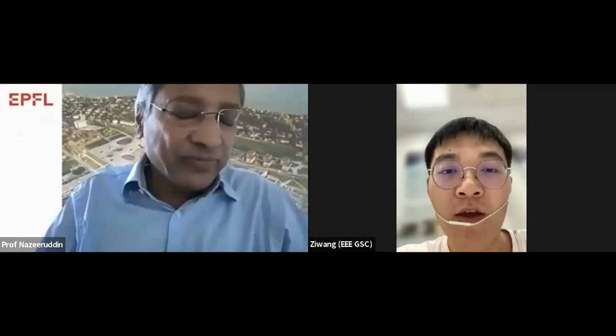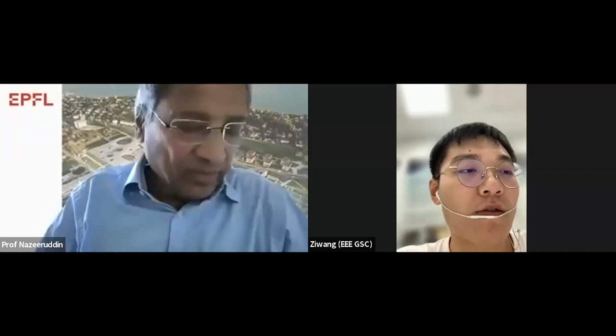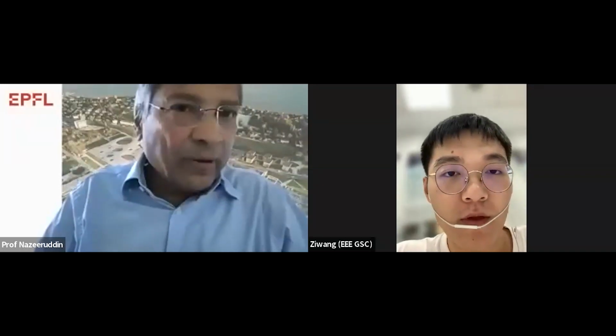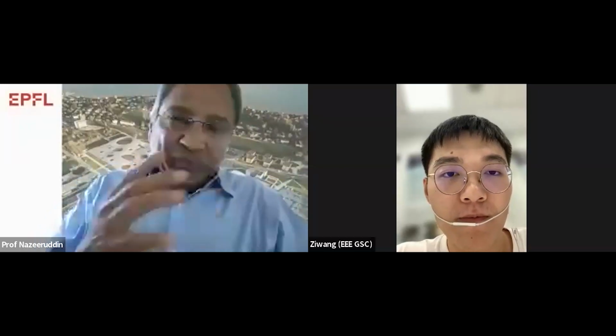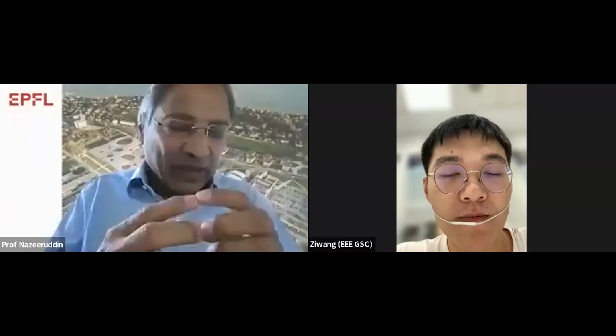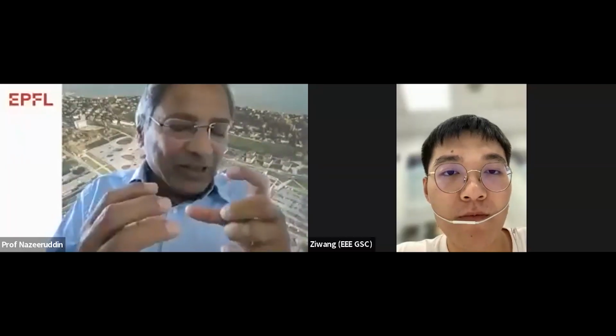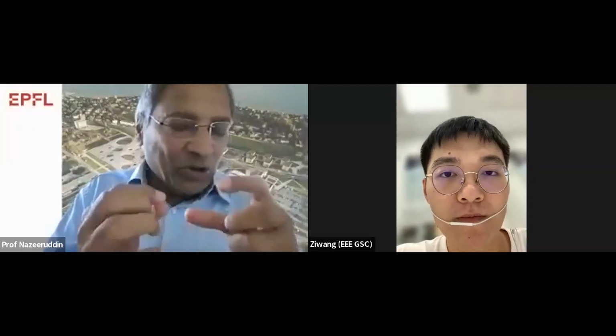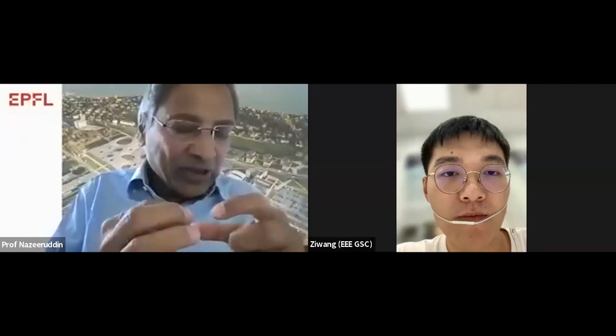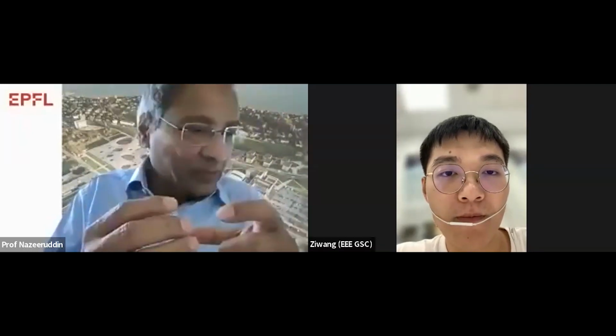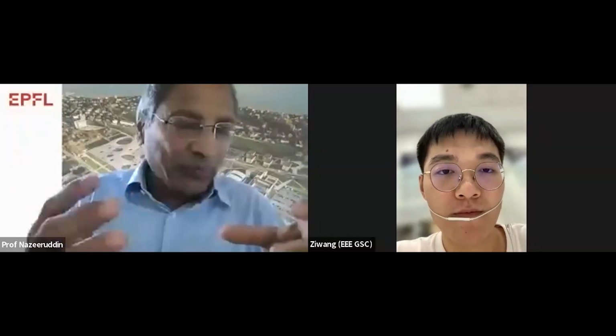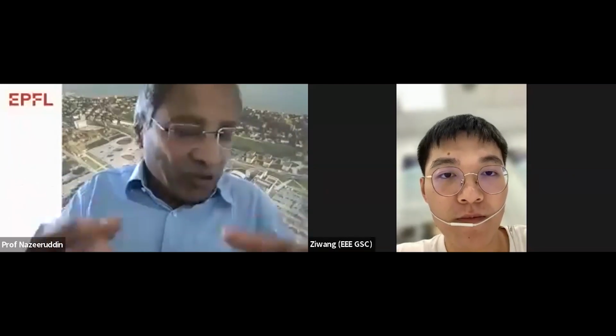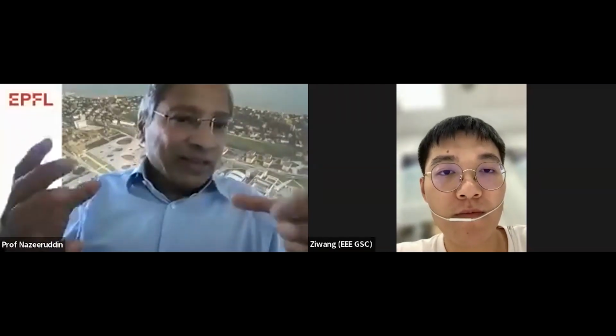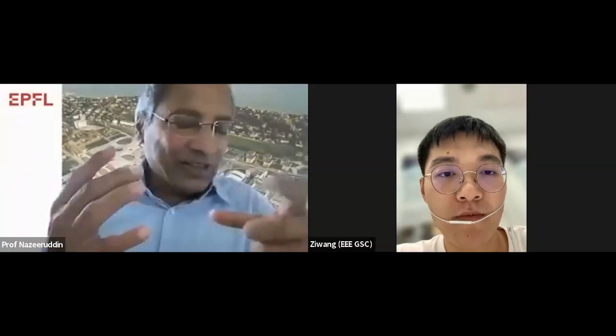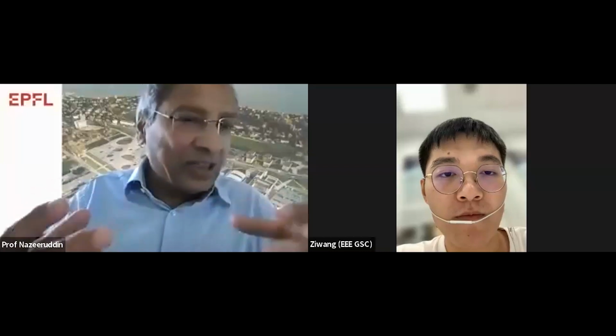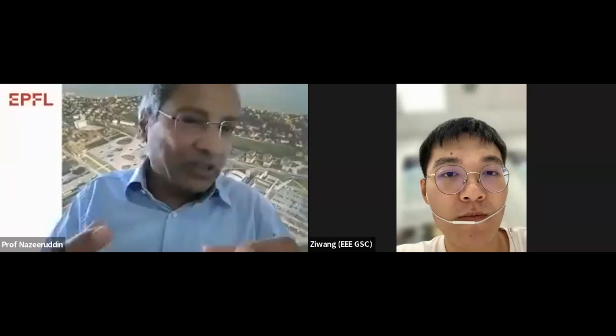Okay, thank you. And the second question is, what is holding back solar panel efficiency? When you deposit perovskite on a smaller cell, the crystallization is very important. This crystallization process, you control on a smaller scale by additives and quenching with different solvents. This gives you enhanced crystal growth. That's the reason you can get the highest efficiency with the smaller cells. When you go to the module level, this crystallization process is different. So this is the scaling up factor: improving the crystallinity of the films, the film formation, is important. So this is the drawback.